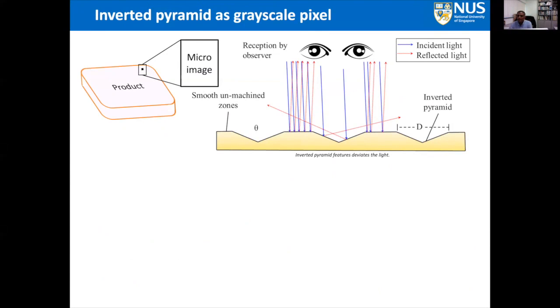Basically, to achieve the visual effect, an inverted pyramid is considered, as it has a simple symmetrical geometry with a squarish aperture. So these inverted pyramid cells can function as the pixels of the micro image, where each cell suppresses the luminance perceived by the observer at the reception location. So the cells will appear dark to the human eye due to the deviated light reflection, compared to the unmachined zone, which appears to be bright.